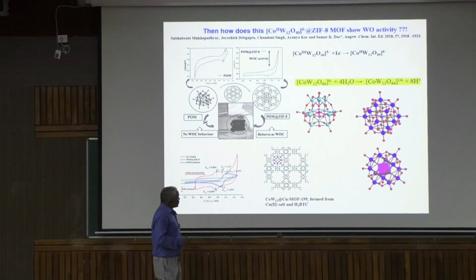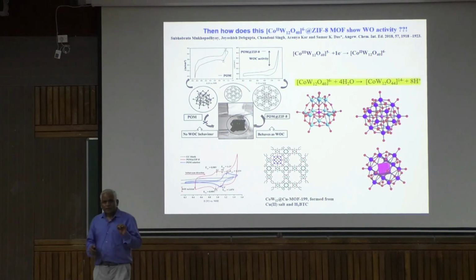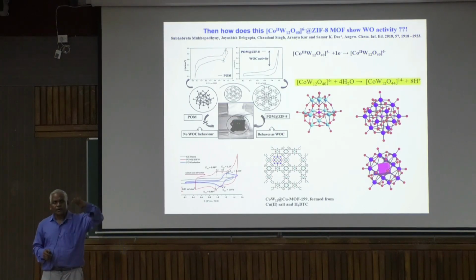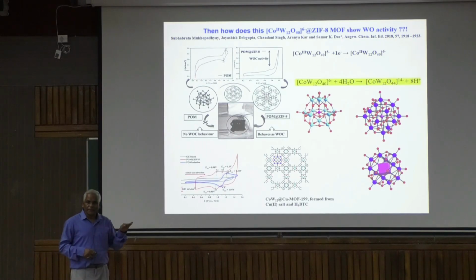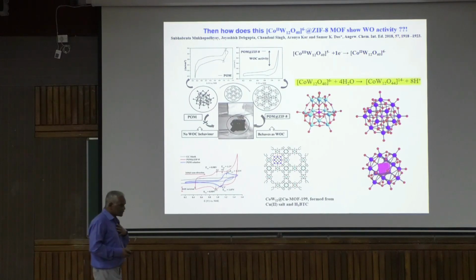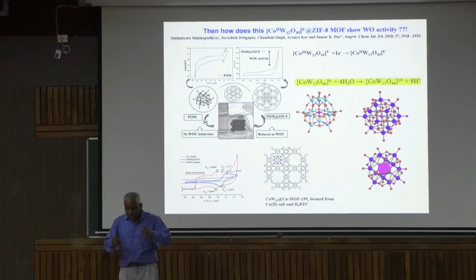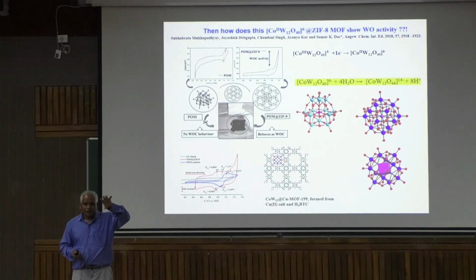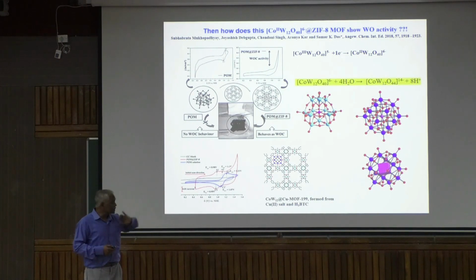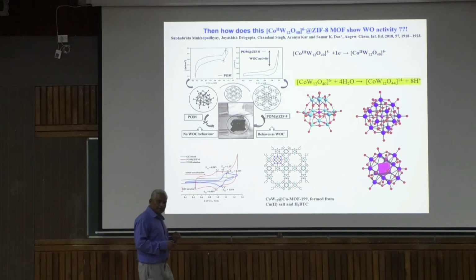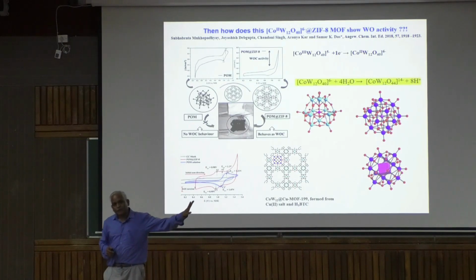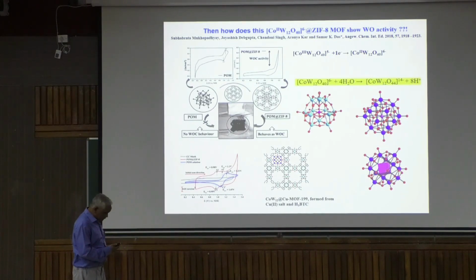So, a very, very surprising thing: as such the compound gives a cobalt 2 to 3 couple, but when we put it inside, suddenly what happens? It gives oxygen bubbles. The question came to us, because we are inorganic chemists: maybe something happened, the cluster got decomposed. But inside the cavity, even if it decomposes, it will be evenly like that, because we characterized everything, we are getting the electron spectrum and all these things. Then in recent time, when we published this paper, we wrote that only, that the cobalt W12O40 was inside the cage earlier.